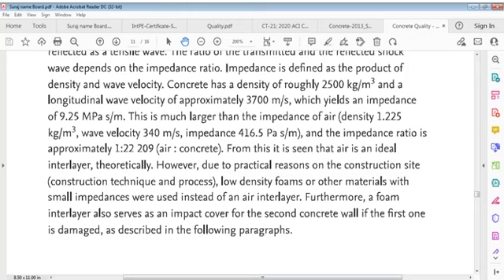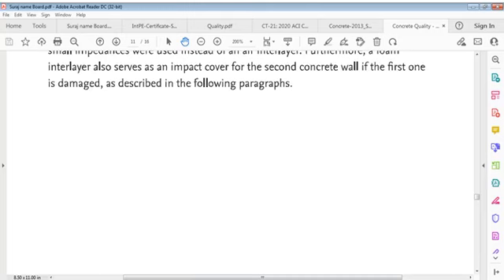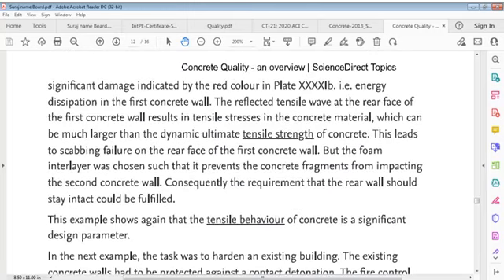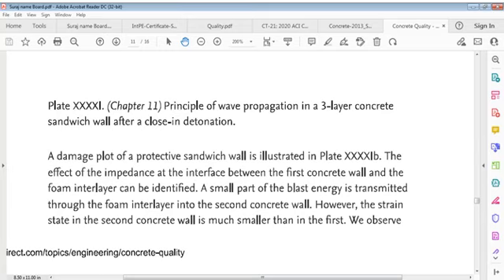Furthermore, a foam interlayer also serves as an impact cover for the second concrete wall if the first one is damaged, forming a protective sandwich wall. The effect of impedance at the interface between the first concrete wall and the foam interlayer can be identified. A small part of the blast energy is transmitted through the foam interlayer into the second concrete wall. However, the strain state in the second concrete wall is much smaller than in the first wall.